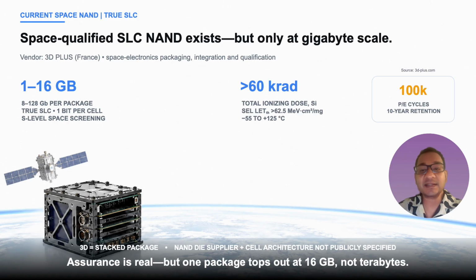True space qualified SLC NAND is commercially available. One example is the Radiation-Tolerant NAND family from 3D Plus, a French high reliability electronics company. These packages provide 8 to 128 gigabits, which is 1 to 16 gigabytes, and space qualified S-level screening is available. The family specifies more than 60 kilorad of silicon total ionization dose, latch-up threshold above 62.5 MeV·cm² per milligram, 100,000 program erase cycles, and 10-year retention.